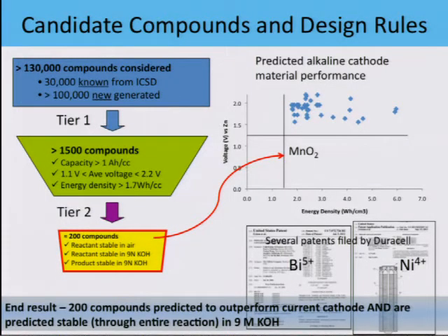Long story short, we screened 130,000 compounds by these data mining techniques and first principles. About 1,500 were a lot better by energy density than manganese dioxide. 200 fit the criteria when you went down to demanding that they had to be stable in air and the electrolyte, and all their decomposition products had to be stable too. Let's say you discharge your battery halfway and then you put it in your wardrobe for a while. You take it out. You'd like to get the last thing out of it. So the decomposition product had to be stable too, which is requiring a lot.